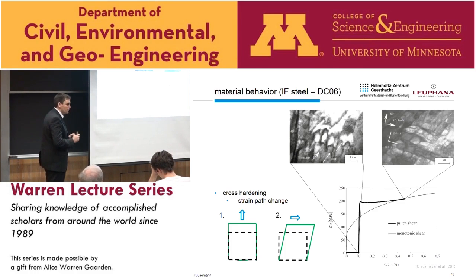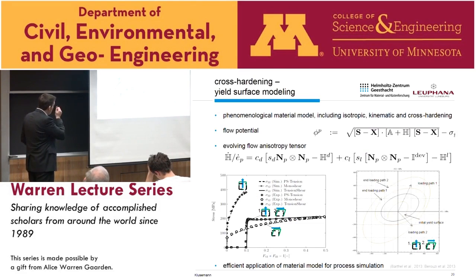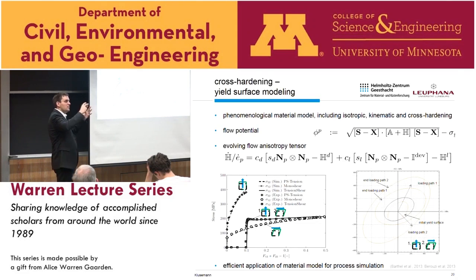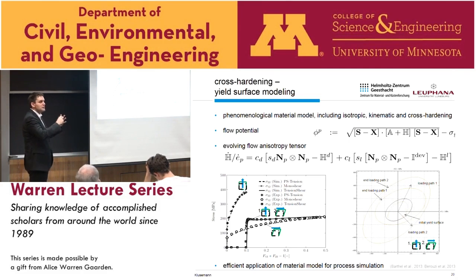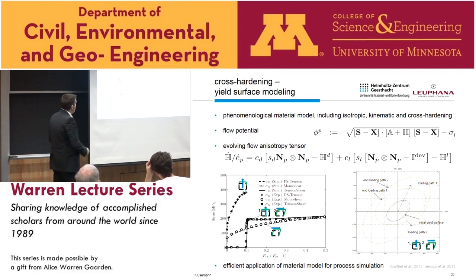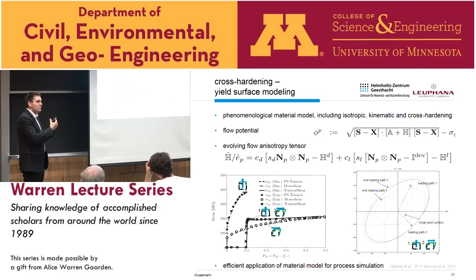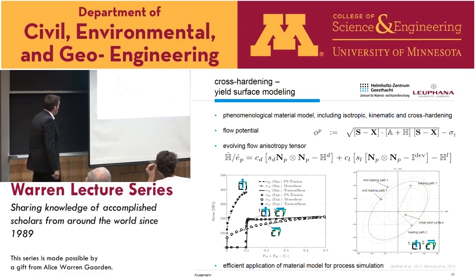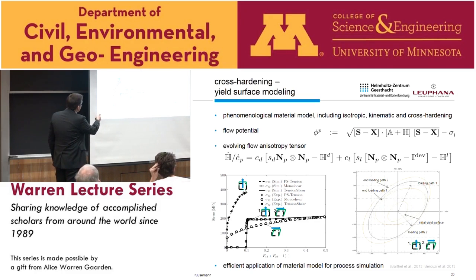So we wanted to incorporate this for a process simulation, so we have to do a very phenomenological approach, of course, but micromechanically motivated. So what we did, we formulated a model which includes, first of all, isotropic hardening. So you can imagine that you have your yield surface, which is just isotropically expanding. Then you have a kinematic hardening contribution, which means your yield surface is moving. It's not changing, it's just moving in space. And then you have a cross-hardening contribution, which actually changes the shape of your yield surface.